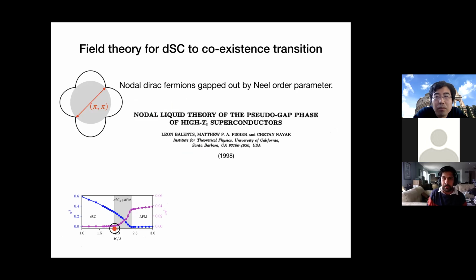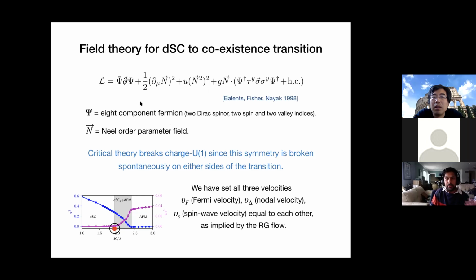It turns out a very similar phase diagram was obtained in some effective field theory description in another context, the pseudogap phase of high Tc. If we have time, we can discuss the motivation behind this paper in relation to our paper. They actually looked at this field theory for this transition already, so we borrowed some of it from their paper. Basically, you can write down the low energy theory for the critical point. It looks like there's some Dirac fermion, the nodal quasiparticles, coupled to some fluctuating Néel order, and this clearly breaks U(1) symmetry, because on both sides of the transition, global U(1) is broken. So that's why there's a psi dagger psi dagger coupling, because you did some rotation. So this is what you get.